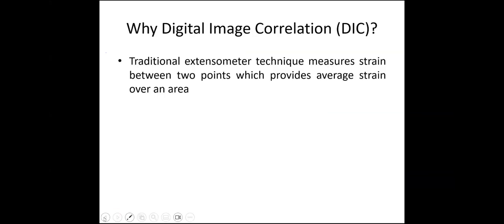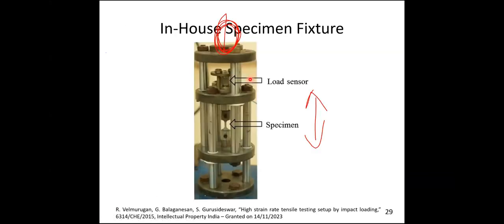So now, if you see this picture here, we have a load cell, the PCB piezoelectric load cell. From this, we get the load data. To get the strain data, we have used a digital image correlation technique, that is non-contact strain measurement. I am going to show it in the upcoming slide. From that, we got the strain data. So from this, we could plot the stress strain curve. From the stress strain curve, it is possible for us to understand the effect of strain rate.